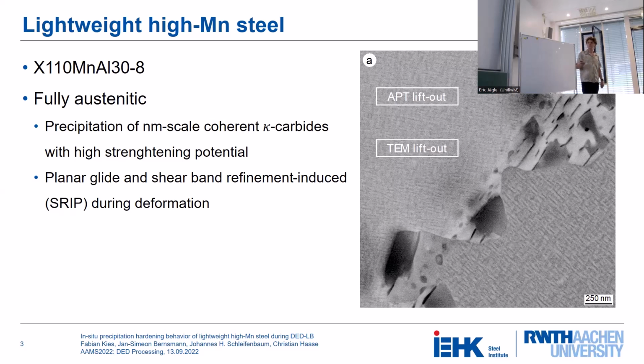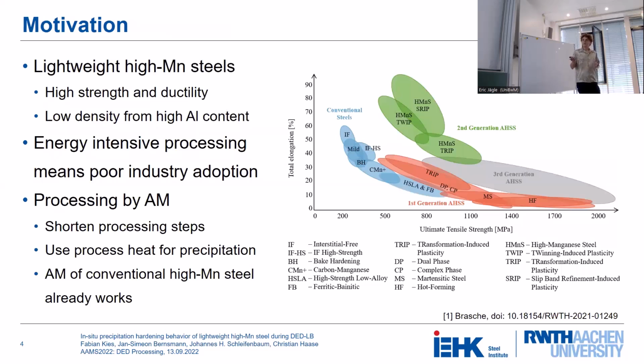Another advantage of this alloy is that dislocation glide is confined to planar glide, which leads to the effect called shear band refinement-induced plasticity. It kind of works like twinning-induced plasticity, where you get dynamic Hall-Petch hardening during deformation. This approach to alloy design is very beneficial, as you can see here in this plot with ultimate tensile strength and total elongation. You can see that these high manganese steels are in the second generation of advanced high strength steel and have a very high strength and ductility combination.